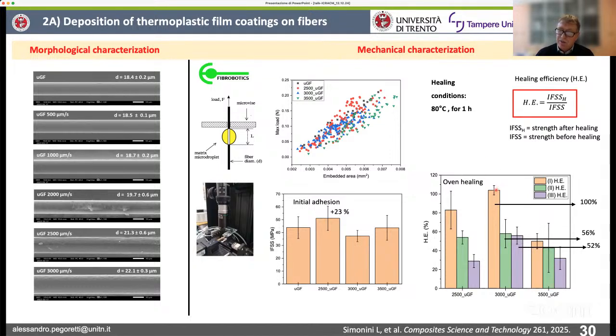But after the first test, we observe a decrease in the healing efficiency. That was quite a surprise. I mean, at the end, we were hoping to be able to restore these mechanical properties more than 1 time consecutively, several times actually. And so we decided to try to investigate a little bit more what was occurring in this case.